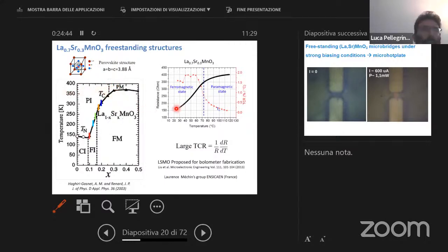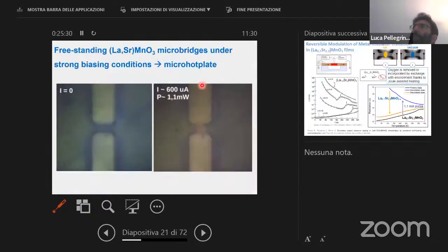temperature. And the phase transition can be detected by measuring the magnetic behavior. At the same time, you can also see the change of resistance is quite large. You have this metallic behavior, and this kink is related to this magnetic transition. And this is particularly interesting, as it has been proposed to make bolometers, because the relative change of resistance with temperature is quite large compared to other materials, and you have also low noise in the resistive characterization of these materials. But I will show you other applications now on these materials, and of course we are making microbridges with manganite.